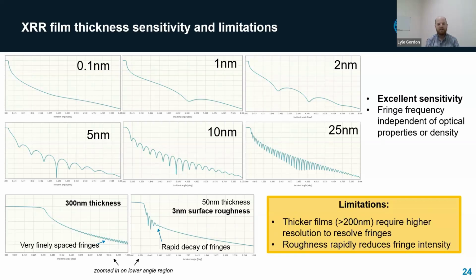And another benefit here of X-ray reflectivity is that the models are quite simple. All you need to know is the density and the interfacial roughness, or you can fit those parameters as well for a few layers. And so you don't need to know the whole optical properties of the material. However, there are some limitations.